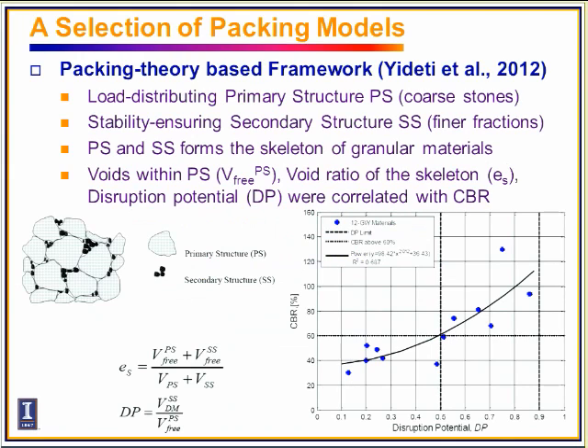A recent paper described a packing theory for unbound aggregates. They calculate the aggregate packing into primary and secondary structures. Based on those definitions, they came up with several important parameters, like void ratio in the secondary structure, void ratio in the primary structure, as well as the disruption potential. They found that the disruption potential is well correlated to the CBR values.